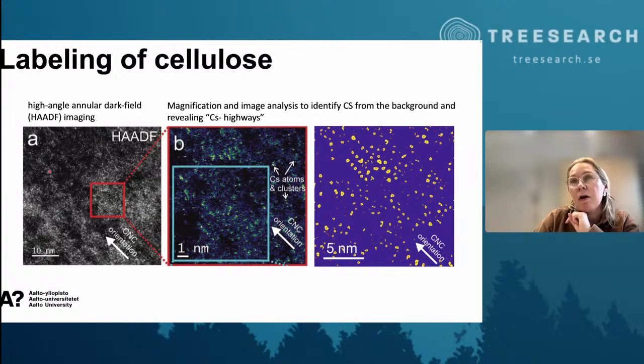And then if we think about the density, so if we think that they would be around the crystals, then there should be some accumulation of them on the edges of the crystals. But we did not observe it in this case. So it's giving some idea that, depending on the location, there's a locality dependence on where the sulfate groups are located.